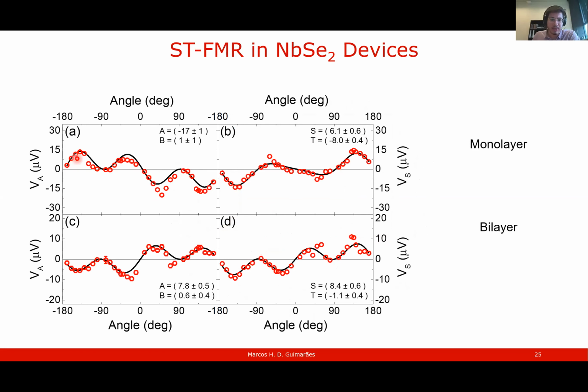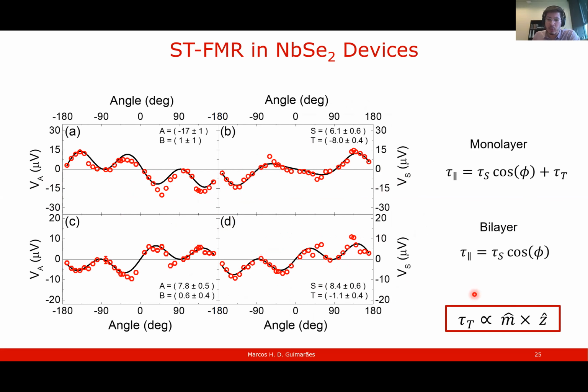And we can do the full angular sweep there, and you can see that for the symmetric component now, the monolayer is very different than the bilayer, while the antisymmetric looks more or less the same. And this would be consistent with the presence of now an odd torque, so a field-like torque, M cross Z, which again is not allowed in the platinum devices because of symmetry. It shouldn't be allowed in niobium diselenide also because of symmetry. So there's something else going on there.